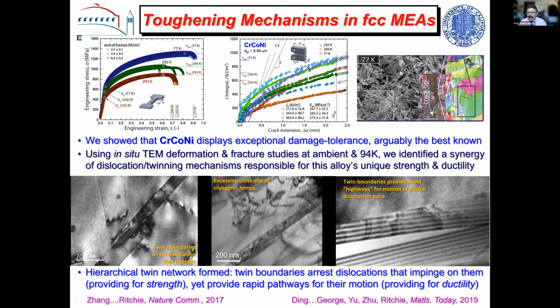And if we look at the microstructures, there's twinning everywhere. This material, because it's harder, twins at room temperature. So again, we have this duality of mechanisms. You can see a twin band here. There's a twinning structure throughout the material. And these twin boundaries actually can arrest dislocations. This is the strengthening mechanism. The dislocation comes up and arrests against the twin boundary.